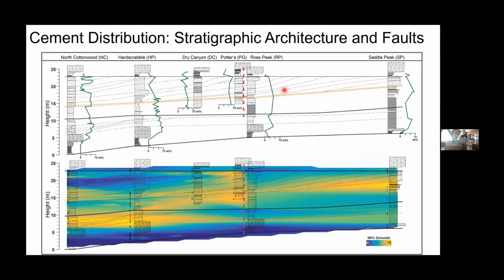Looking at the stratigraphic architecture and the relationship to those deep-seated faults yields a different story. So these are the same cross-section that I showed earlier, but now I've taken the facies off, and I'm only looking at the clinoform boundaries and the major stratigraphic surfaces from that cross-section. So the clinoform boundaries are the dotted lines, and the major stratigraphic surfaces are these solid lines. Then plotted next to the outcrop is the weight percent dolomite from XRD for each one of these outcrop locations. So you can see how that varies next to these stratigraphic surfaces. And then the red line here is that fault that I alluded to.